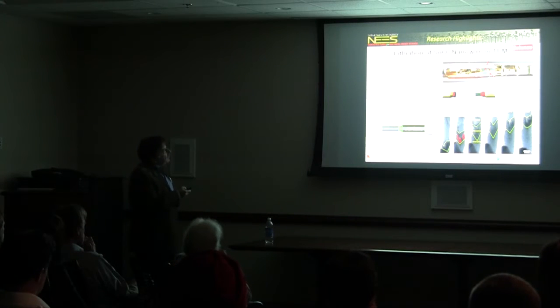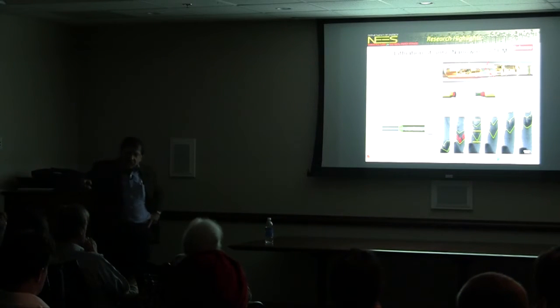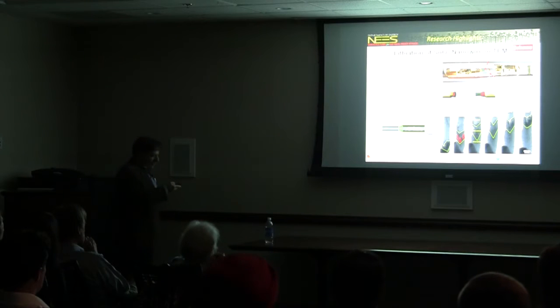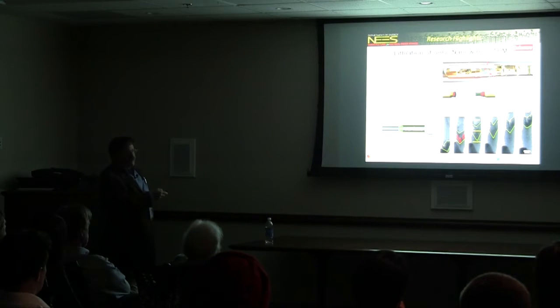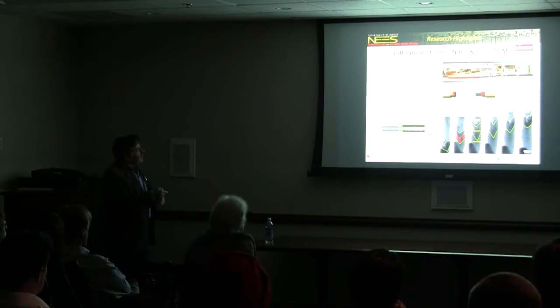So let me give you a couple of highlights. I think I have a few minutes for this. So this was one of the first ones that came along in Science Magazine. It's apparently on Bill Brinkman's list for showing off to Congress in terms of funding all of this, so we're delighted about this. So this was Jianyu Huang's work at Sandia, and what he did is he made this little structure that goes into a transmission electron microscope, which gives you atomic resolution. And on one side, you have a little wire of lithium cobalt oxide. This is a cathode material. This is an ionic liquid, a drop of electrolyte, which you can actually put in a vacuum. It doesn't evaporate very fast. And with another manipulator, bring a tin oxide nanowire and put it into this little droplet. So this is a nanobattery.